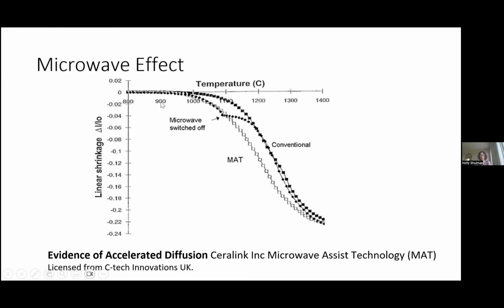And these 3 samples, you can see just a conventional regular heating, and this is linear shrinkage, measured with a dilatometer. You press a long skinny pellet basically, and then see how that shrinks. And in a conventional way, this is alumina, a high quality sample that is just one material, so it's not a composite like all these other regoliths are. And you can see how it shrinks and at what temperature.